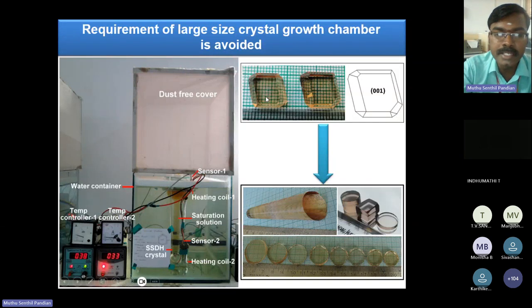You see, this is the seed crystal of SSDH, sodium sulfate decahydrate single crystal. In a beaker, we have grown this crystal. Using single crystal X-ray diffraction, we identified the morphology. So we tried to grow the crystal along its C direction, because the growth rate along this direction, the C direction, is very high compared to all the other directions.